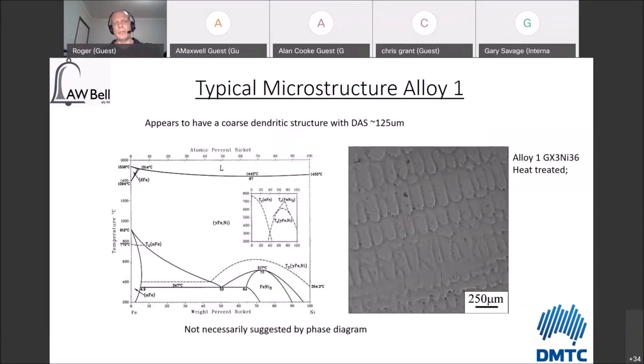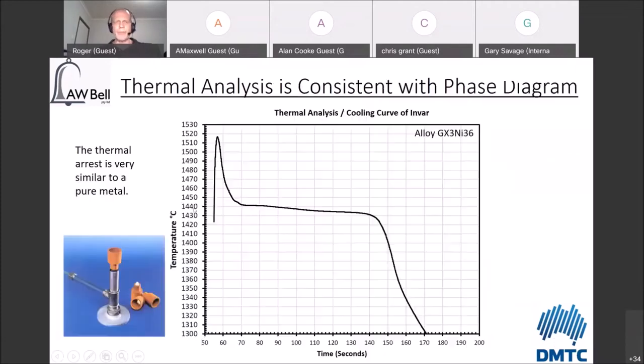So this was an interesting thing because the background of the hot tearing becomes a little bit more complex, and it's still something that I'm working on. But it is very, very important to make the note that it does go through this direct solidification, direct from liquid through to solid. And when we look at the thermal analysis of the material, we can see that the thermal arrest is very, very similar to a pure material.